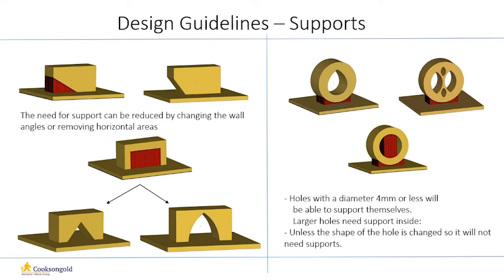We can angle these supports out slightly to reduce the damage caused to the part, but ideally we would like no support within the hole, because otherwise it's very hard to access that area to clean it and finish it. So you can change the shape of the hole so it won't need supports. You can see above they've changed it to slightly triangular to be self-supporting.